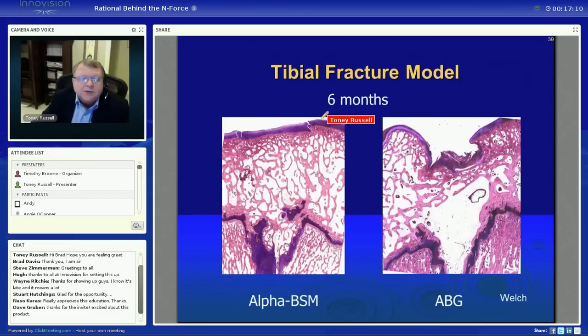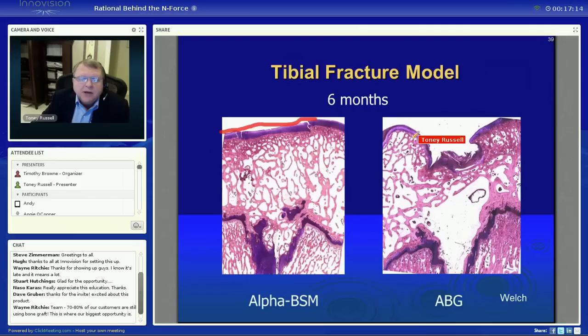What happens a little later? Well, this is at 6 months. In 6 months, our articular surface is still lined up nice and straight. What we see in the bone graft group is collapse of the articular defect. This will lead to arthritis, not just on the tibial side, but also the femoral side that's supposed to be articulating here like this. And you look, this one actually had a void. So the graft material was actually completely removed as dead material and left a hole. So it's structurally not regenerated.